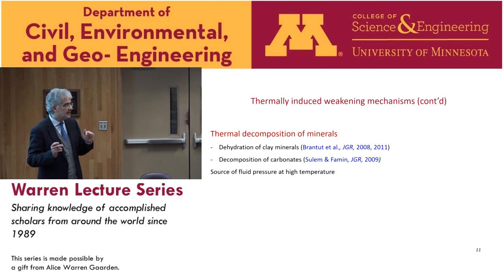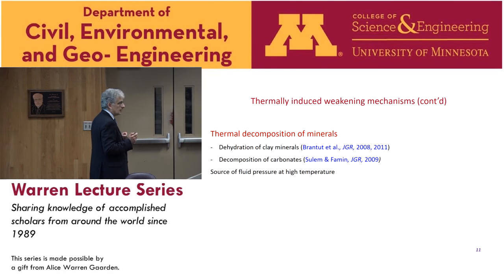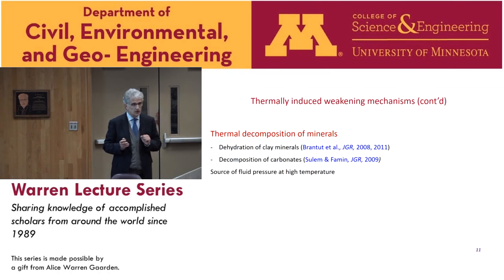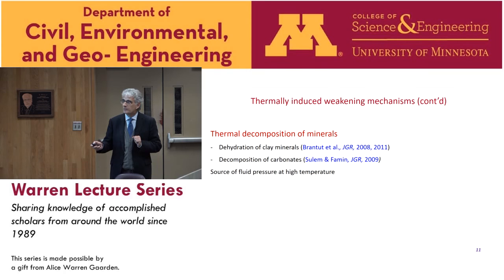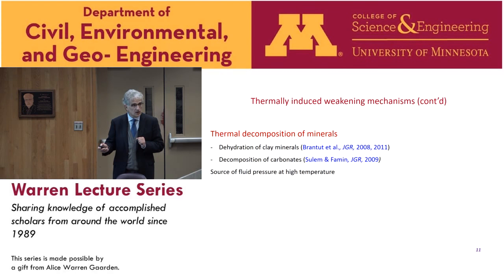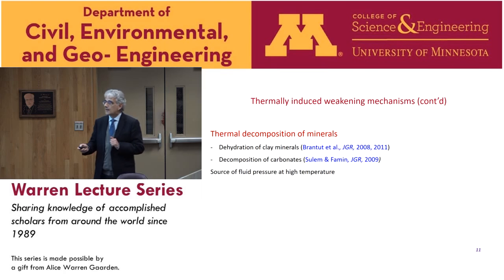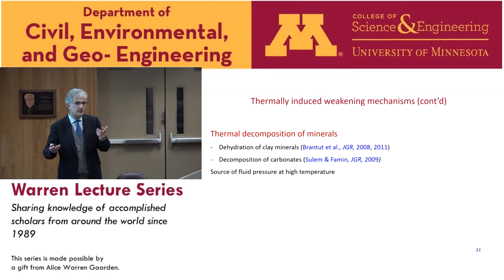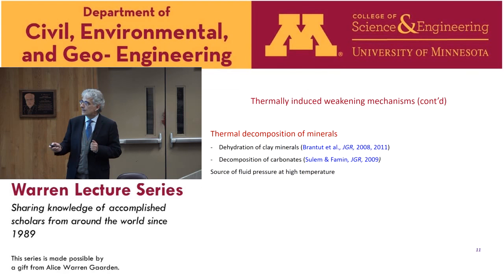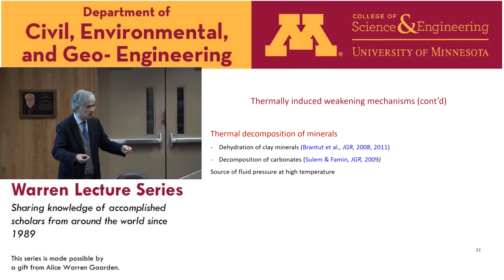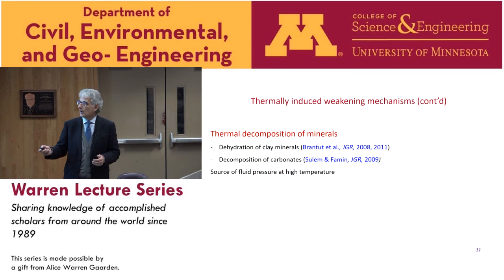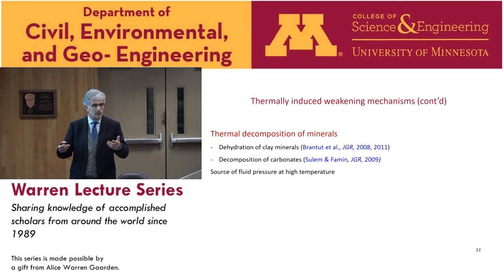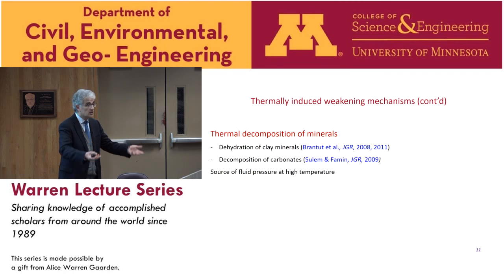If the temperature rise is sufficient, the onset of chemical reactions can be triggered in the form of thermal decomposition of minerals, typically dehydration of clay minerals above a few hundreds of degrees, and decomposition of carbonates above about 700 degrees. And this type of reaction will release an additional fluid phase into the system because dehydration liberates water and decarbonation liberates CO2. So this source of fluid at high temperature will contribute to an increase of the pore pressure.